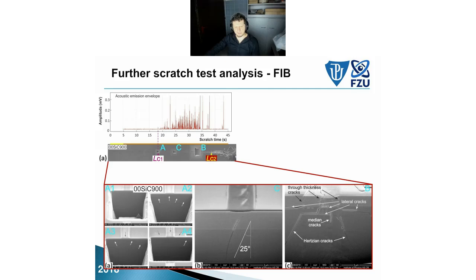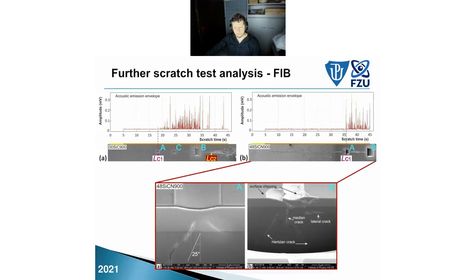It's a very brittle system. Silicon carbide can be very brittle at high temperature, and silicon carbon nitride here, this is the highest concentration of nitrogen in silicon carbon nitride we had, and as we saw, we couldn't see anything from the surface. We saw something from the depth change, but not for sure. But we heard it using acoustic emission, and we analyzed the points where the acoustic emission arose, and we just saw nicely. Here, silicon carbon nitride.